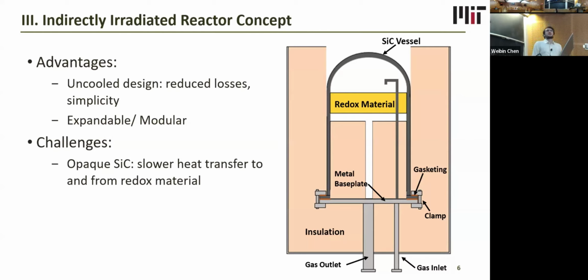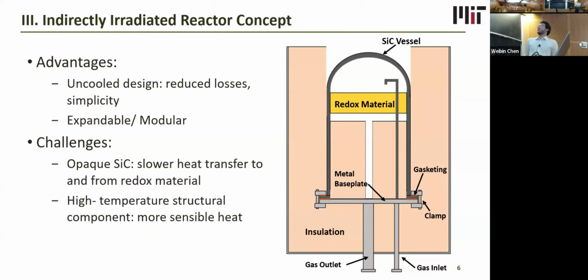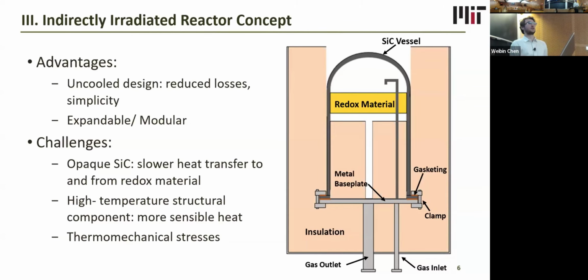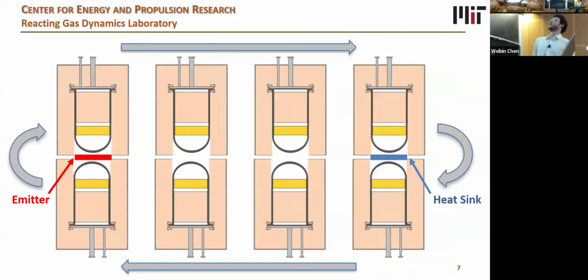Now, the challenges of using a system like this are that we're using opaque silicon carbide, which means we're going to have slower heat transfer to and from the redox material because it needs to heat up to re-emit. Since we're also going to have a high temperature structural component, this means we'll need to use more heat to get it up to temperature. And it will also experience significant thermomechanical stresses, which will need to be seriously considered. I'll show that in the next few slides.